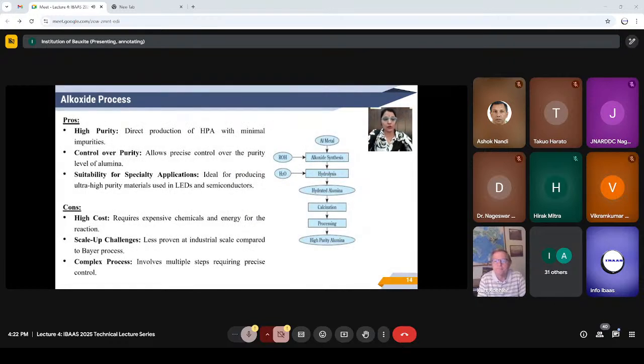Next is the alkoxide method, which I have used in JNARDDC to produce high purity alumina. So this alkoxide method is a chemical route to produce ultra high purity alumina. And it is not starting from the bauxite, but it is starting from the pure aluminium metal. So this process is particularly suitable when our end goal is to obtain 99.99% or even higher purity alumina, which is required in LEDs, semiconductors, and sapphire substrates.